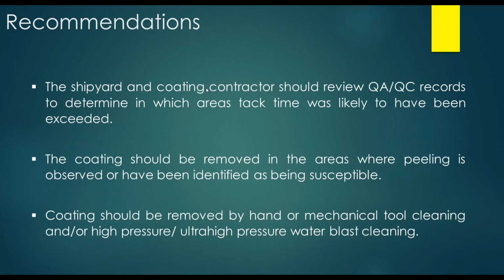The best way I can address that is that delamination that you see when the coating is in its service environment is affected by a number of factors. It could be the wave action, it could be water penetration, none of which can be accurately replicated in a lab. And when we did our testing, it was a simple tape test on top of either the X hatch or a cross hatch. So the physical manifestation of the delamination is most likely a result of limitations of laboratory testing.